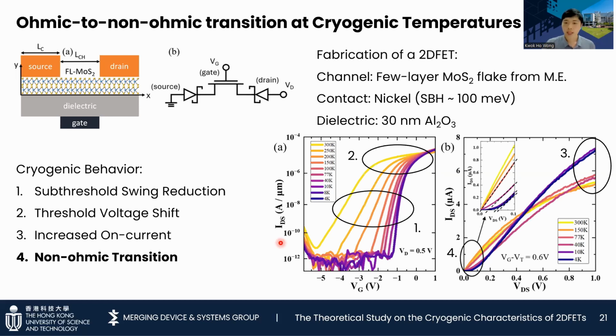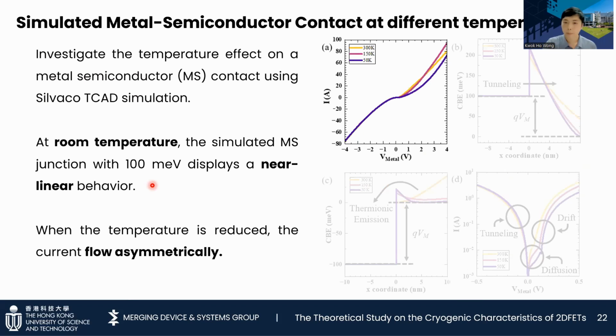To experimentally validate the ohmic to non-ohmic transition, 2DFETs are fabricated with the cross-sections shown in these figures, while the device parameters are listed on the right side. We intentionally picked nickel as the contact electrode to match the reported data and to achieve ohmic contacts at room temperature. When we measure the fabricated device at different temperatures, we observe four different behaviors: SS reduction, VT shift, increased on current, and the non-ohmic transition. To study the mechanisms behind these transitions, we investigate the temperature effects on the contact part.